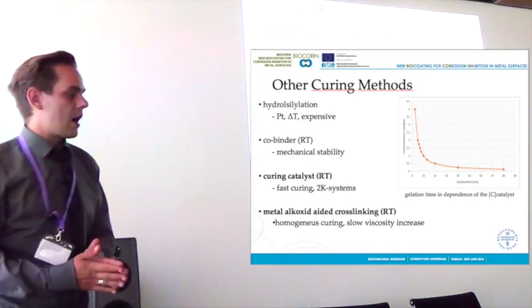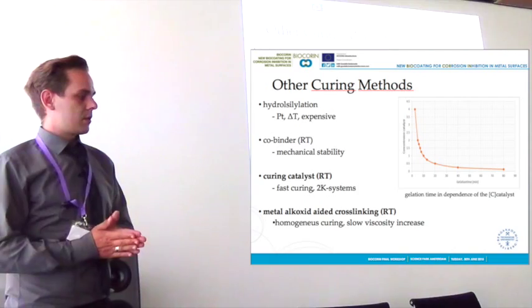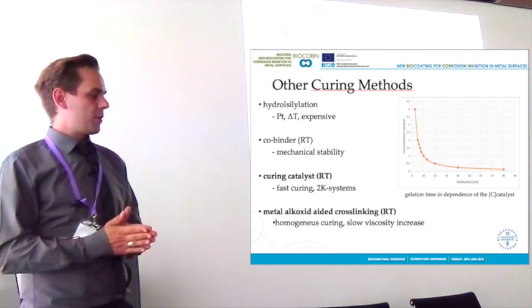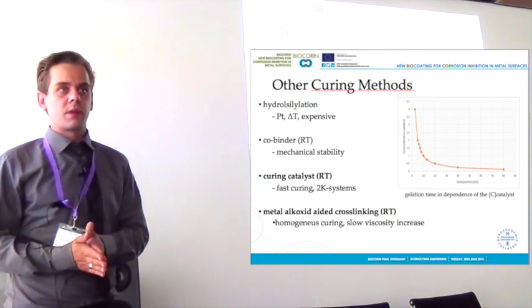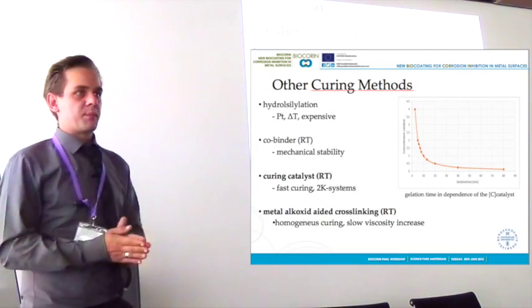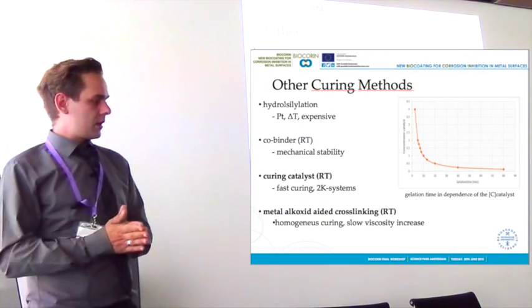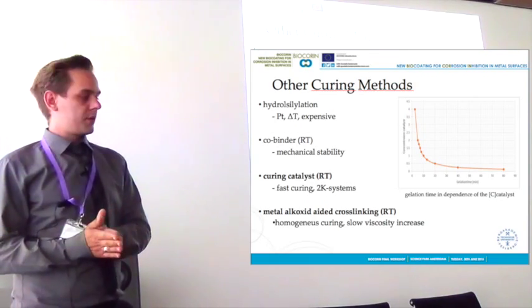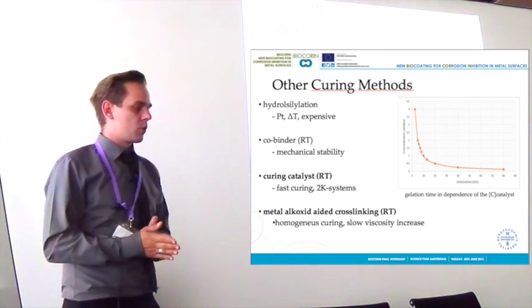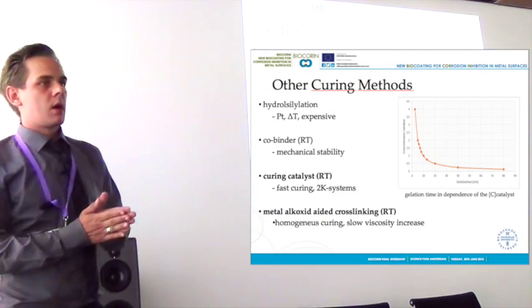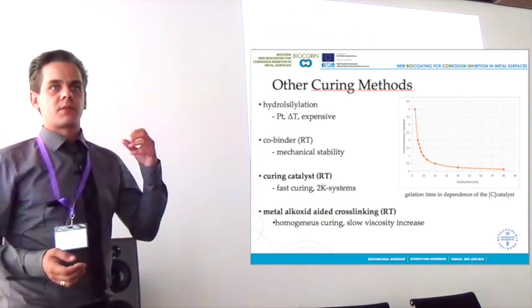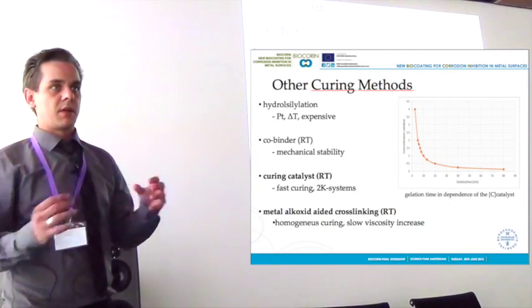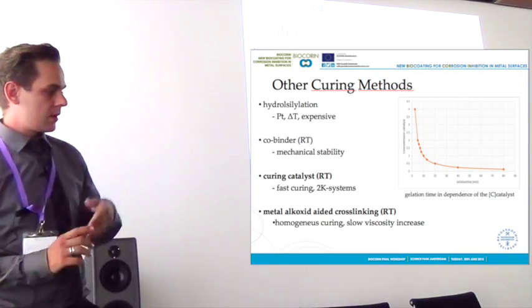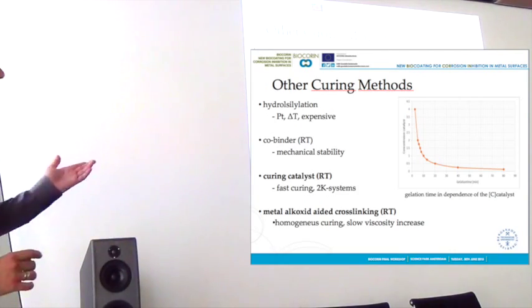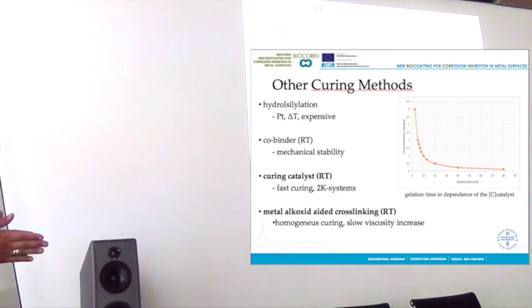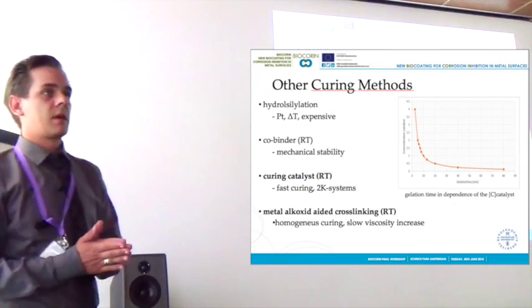Other curing methods are hydrosilylation. People that are familiar with silicone chemistry will know it. It's quite expensive, because you need platinum and you need temperature for the curing. Another method would be to use a co-binder, which can react with a sol gel binder, so you get a dense material if both components are mixed. Another method that we used a lot in the project was to add a curing catalyst.